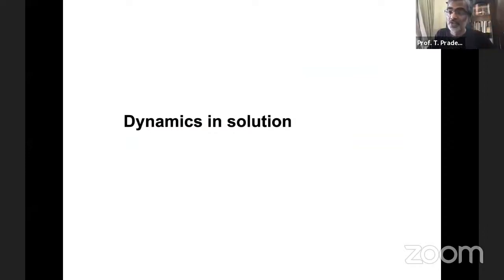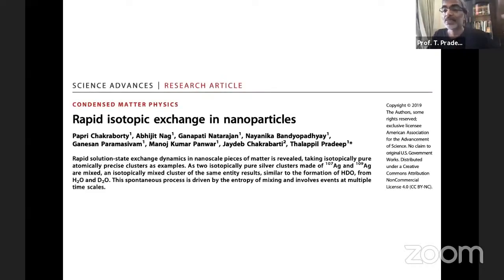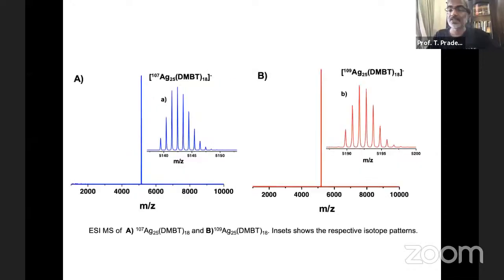What it also tells you is that if I have one cluster and another cluster, they are exchanging atoms. Within one cluster itself, atoms can be exchanged. And this is something that we saw by taking isotopically labeled clusters. So here is an isotopically labeled cluster. Here is another isotopically labeled cluster. This is pure isotopes, not just labeled. You have your pure isotopes of this silver 25. This is another isotope of silver 25. This is all that is present.